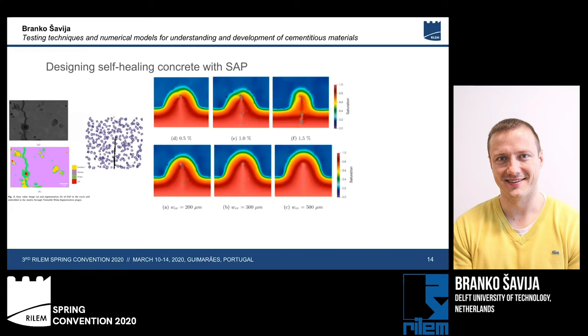We can easily vary the amount of SAP particles, ranging in this case from 0.5 to 1.5%. And we see that as we add the SAP particles, the penetration front becomes narrower. What we can also do is check the influence of different crack widths. And we see here that if cracks are quite wide, there's not much we can expect from these SAP particles. We can also play with the properties of the SAP particles, because the swelling capacity of different chemistries is different.